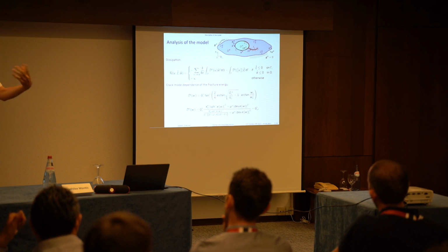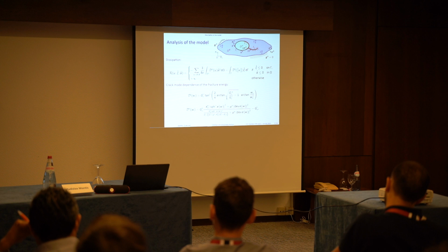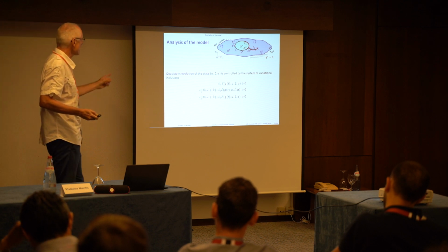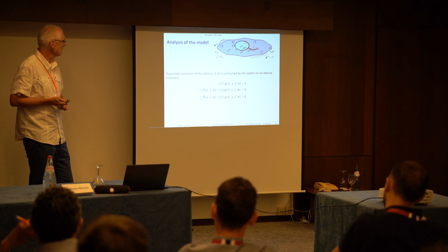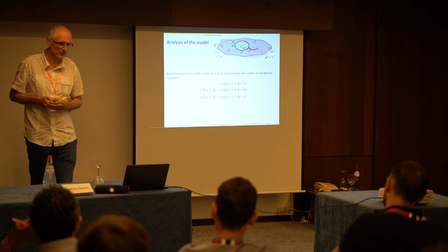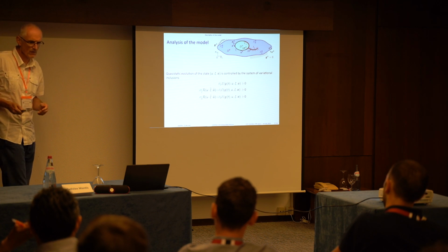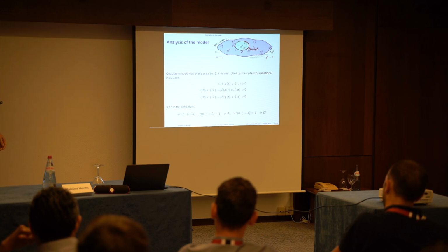So this is the additional dissipation to the GC1, which is in mode 1. In this way we have this additional energy, and we may look at how the evolution of the system can be described. In a quasi-static evolution, we may describe the solution by this system of variational relations, which are solved from the initial condition.